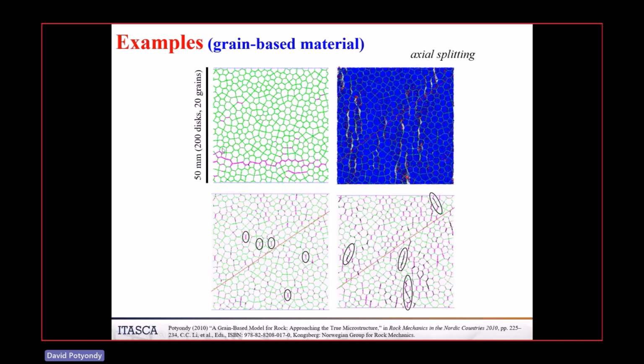This up here is the final state of a direct tension test. And you can see what's happened here is that this pink is microtensile failure, and a predominant fracture has grown across this specimen. There's been a little bit here and a little bit here, but they didn't go all the way across to make it fail. These are all microtensile cracks.